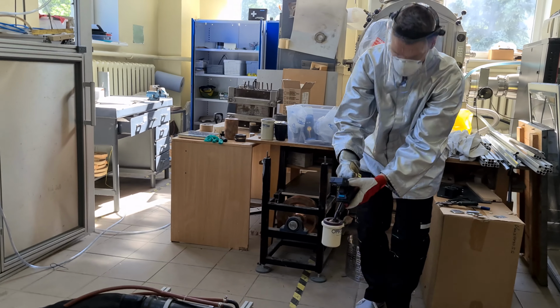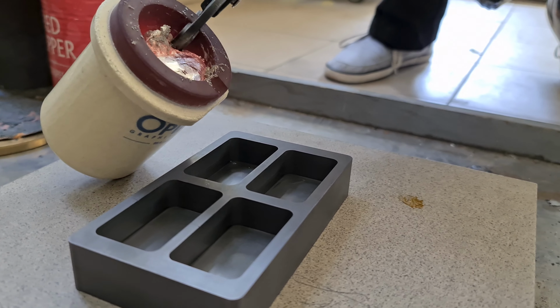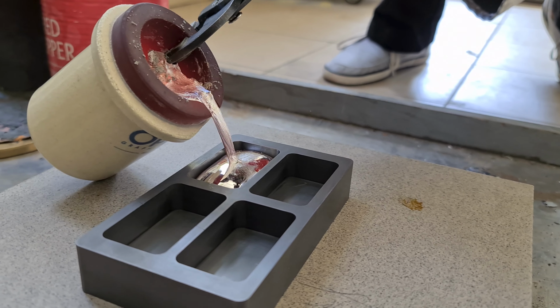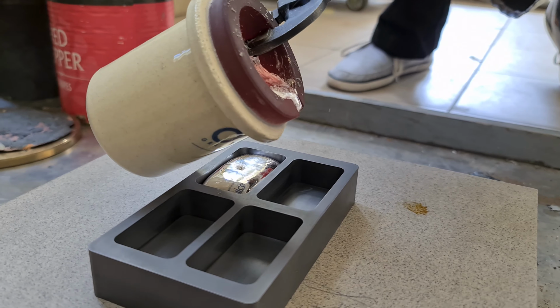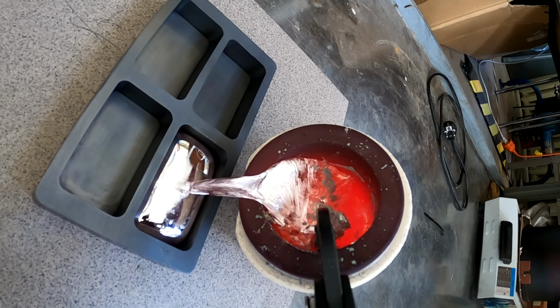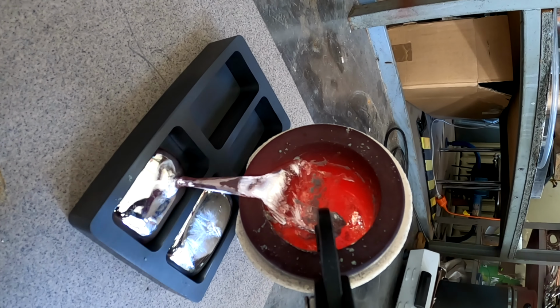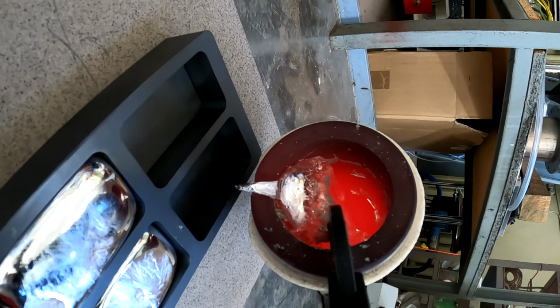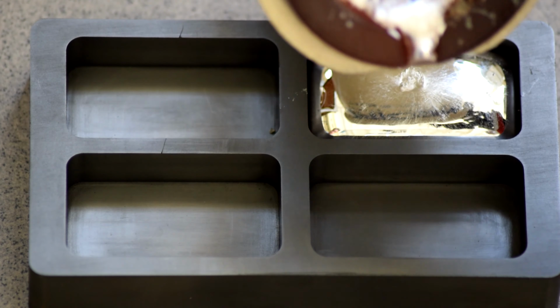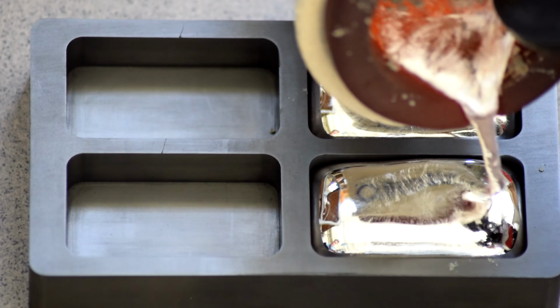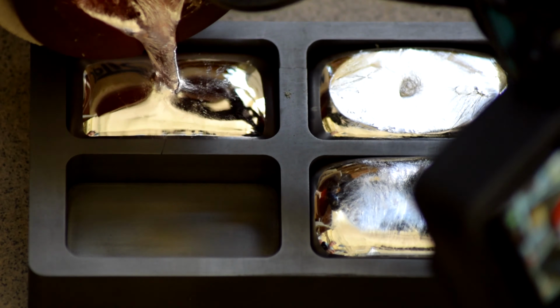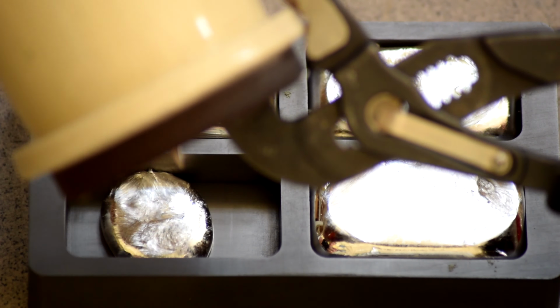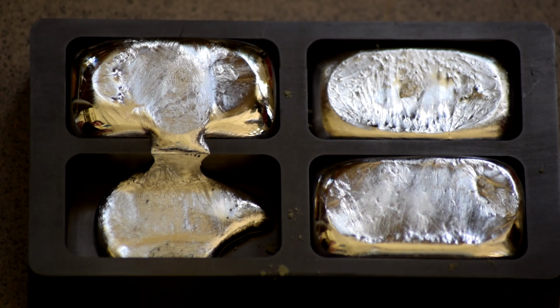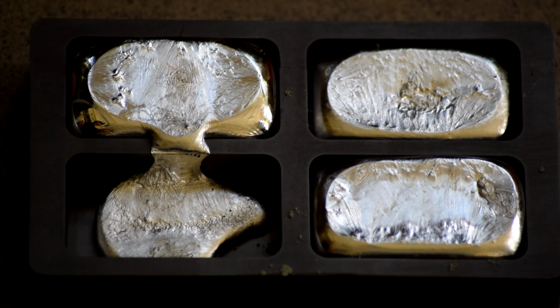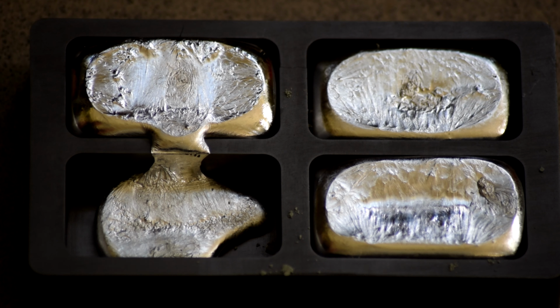When a composite sample is created, we pour the processed aluminum into a graphite crucible, thus making small sample ingots to be examined later. Here is unique point of view footage of that happening. You can see the phase change and follow the solid-liquid interface as metal solidifies. Another visible change is in density. Solid aluminum is denser, thus it takes up less volume, and this is the root cause of many casting defects.